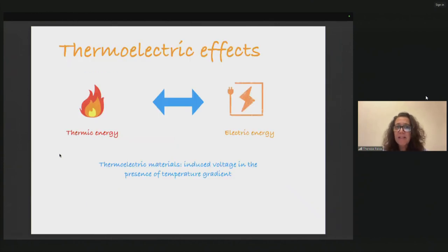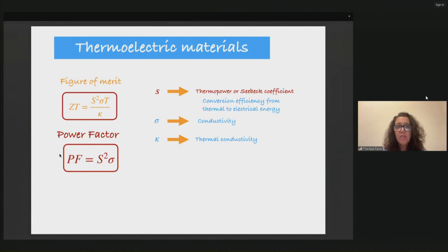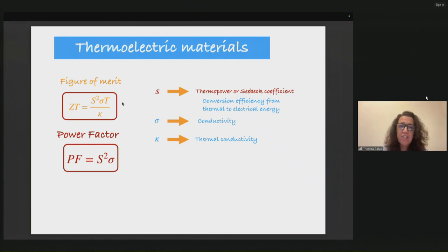The talk summary: I'll start by talking about thermoelectric materials and thermal power, then turn to the models we have studied, and then the specific Seebeck coefficient we address here. We are concerned both with geometrical effects and with the role of extended correlations and different types of correlations in the Seebeck coefficient, and then I'll come to conclusions. Simply, thermoelectric effects are those in which thermal and electric energy are joined — when an induced voltage generates a temperature gradient, or when a temperature gradient induces a voltage — and this has a huge set of applications. To quantify thermoelectric effects in a material we use the figure of merit, a dimensionless quantity that depends on the Seebeck coefficient — which measures the conversion efficiency from thermal to electric energy — the electrical conductivity, the thermal conductivity, and the temperature. We also look at the power factor, which depends only on the Seebeck coefficient and the electrical conductivity.